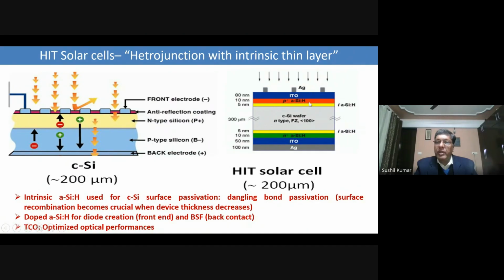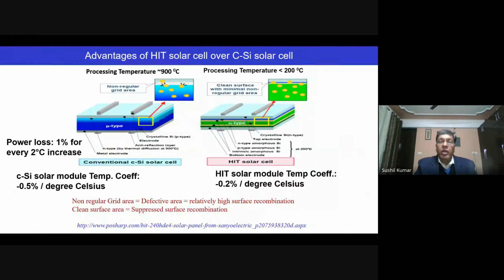So basically your junction is forming here with your P-type and the N-type silicon. And this I layer is very, very thin, less than 5 nanometer, or maximum 5 nanometer it is used. This is for passivation of crystalline silicon. This passivation improves the overall efficiency of this cell, and over it you have a heterojunction with amorphous silicon. It is also done on the bottom side, then ITO and Ag. ITO is for collection and is transparent, so light can go in, and you have a metal contact. All thicknesses are given here. So this is how it looks different from the conventional crystalline silicon cell, the amorphous silicon based heterojunction solar cell. This is also quite popular nowadays, and this is much, much better.